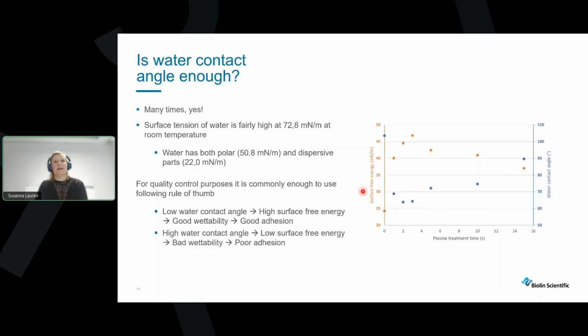And as I said, many times the contact angle measurement with water is enough. If we look at this graph here, this is where we have looked at the surface free energy and the water contact angle as a function of plasma treatment time.